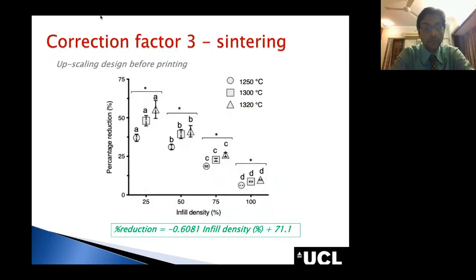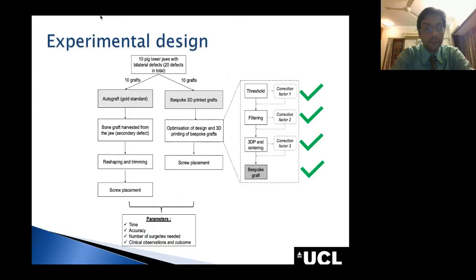We used that equation to have our correction factor number 3, which is due to sintering, and that was used to scale up our graft before printing. So after all these 3 factors were taken into account, we finally 3D printed our grafts and performed the surgery.